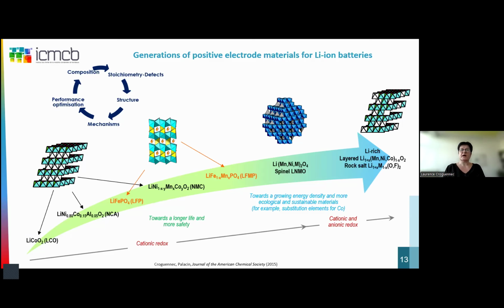We can see that you have different chemistries here along this arrow, and at first the motivation was really to go towards, I would say, longer life, more safety for all these materials, moving from lithium cobalt oxide to NCA, nickel cobalt aluminum, and NMC, nickel manganese cobalt. And in that case, we were really playing with the cationic redox.